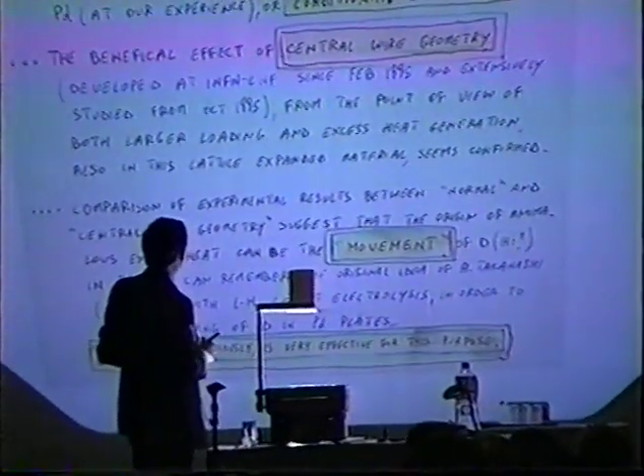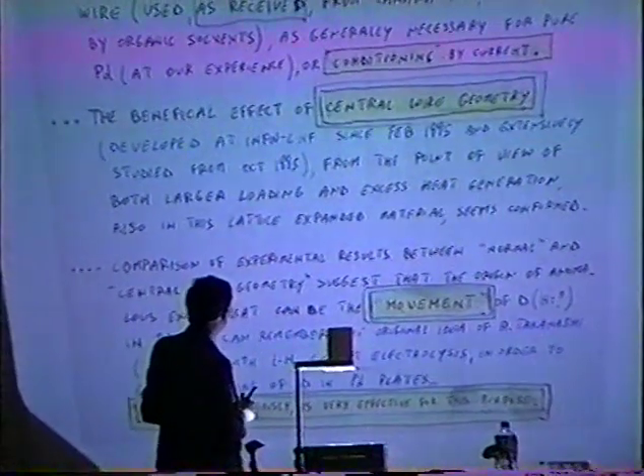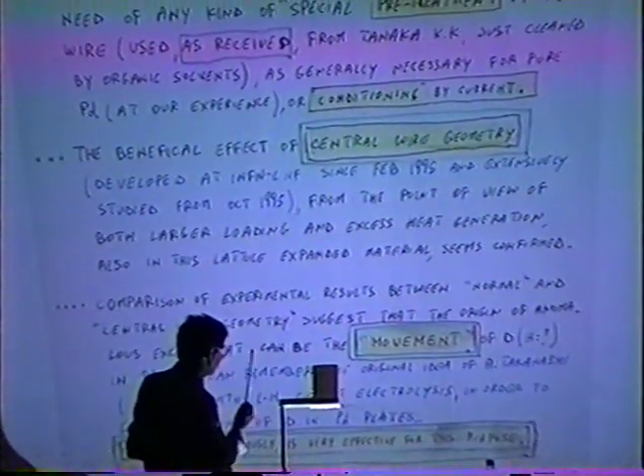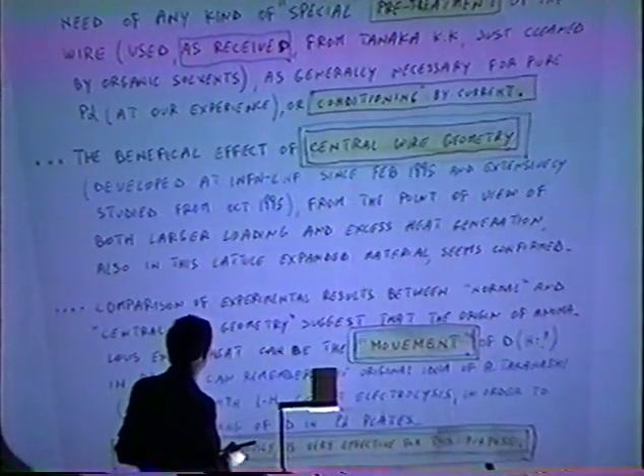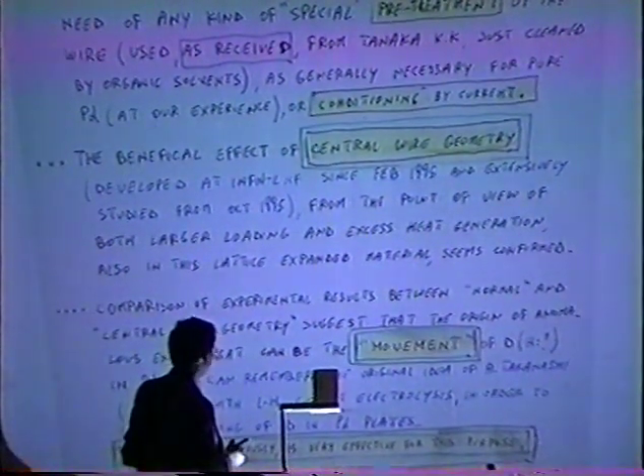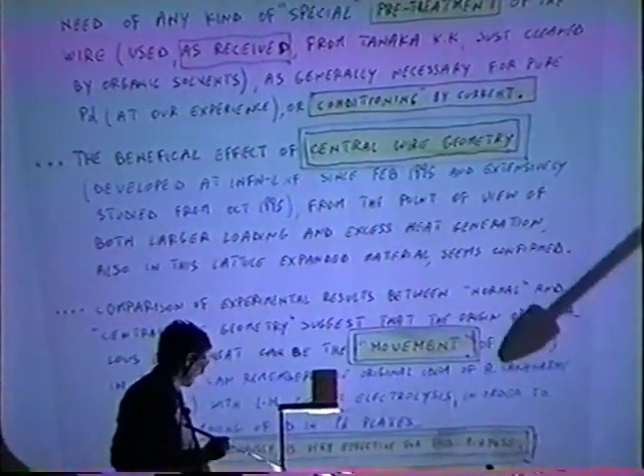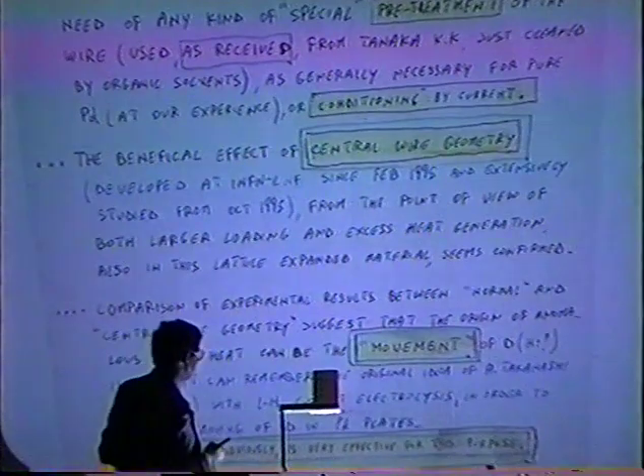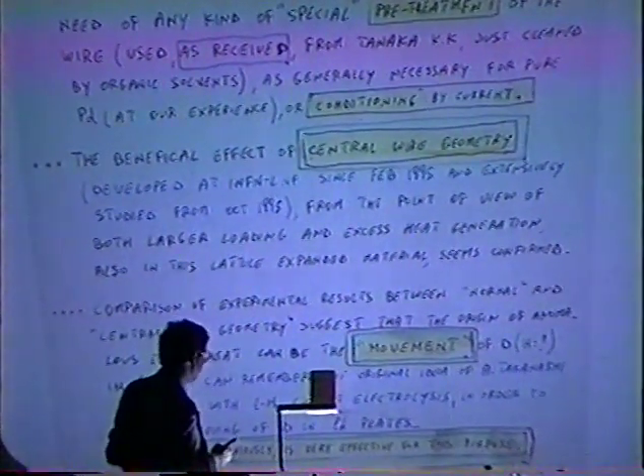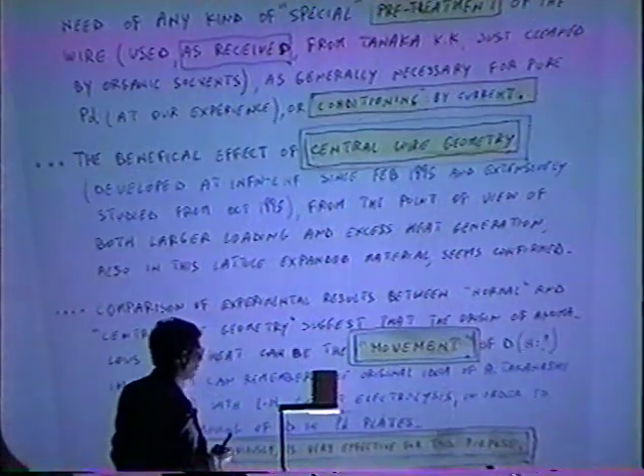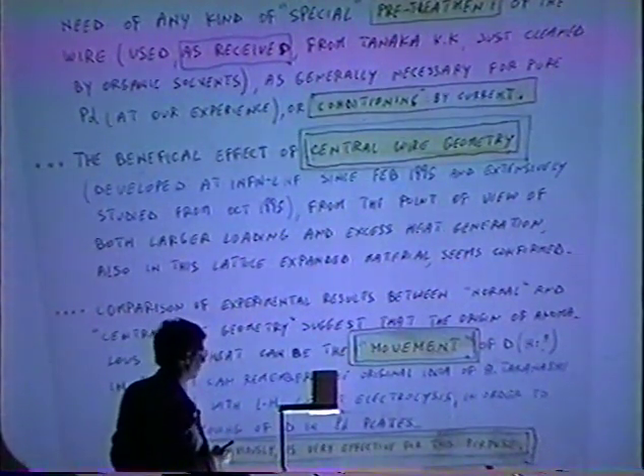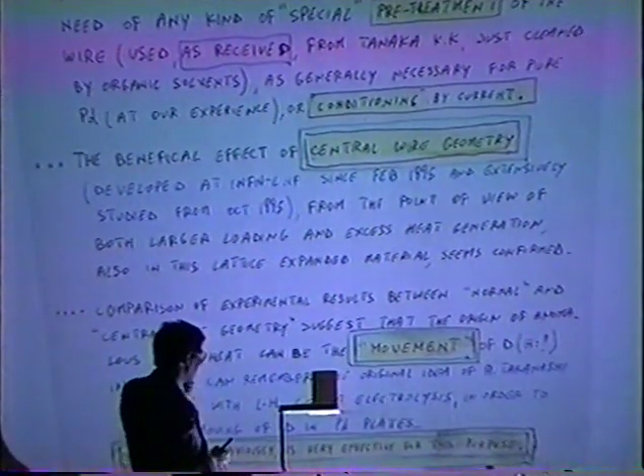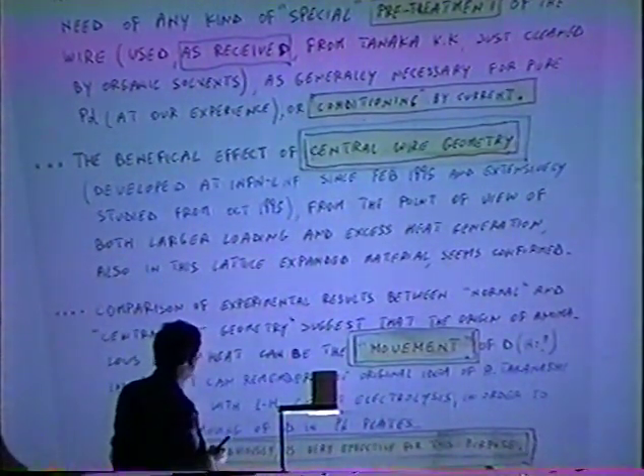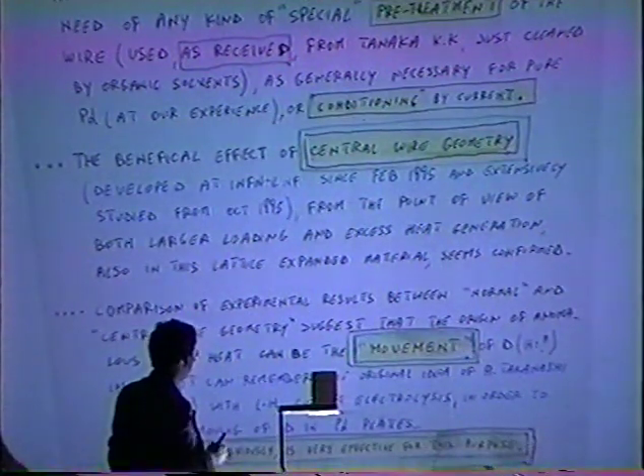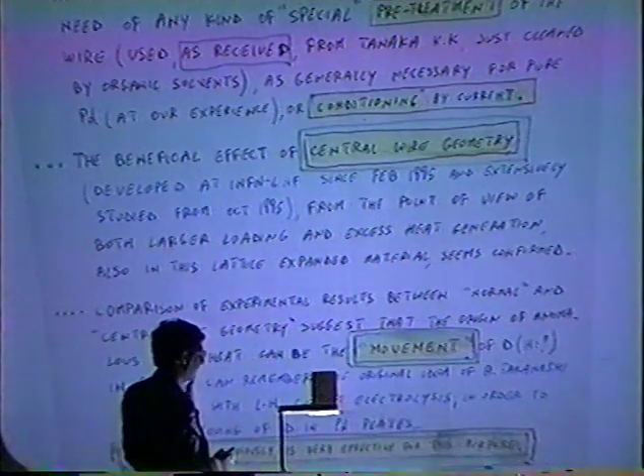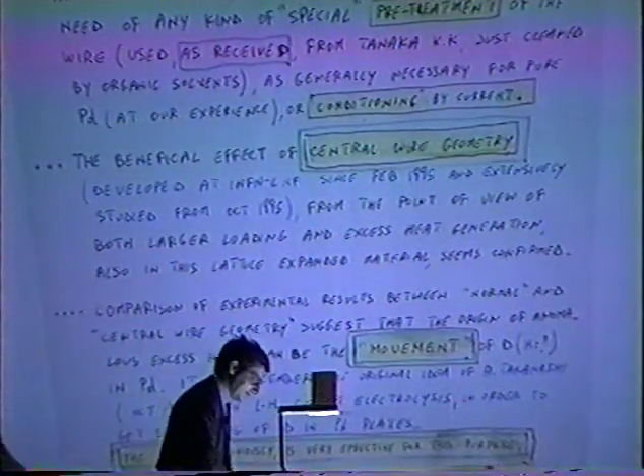The beneficial effect of the central wire geometry, said about a year and a half ago, seems in this kind of material very, very strong, and confirms what we have found with pure palladium. So we are strongly thinking that the origin of the excess heat is the movement of the deuterium inside palladium when some large loading is reached. So together, large loading and moving. Obviously, the pulse condition is very effective to have strong moving because of very large current density in a very short time. Thank you.